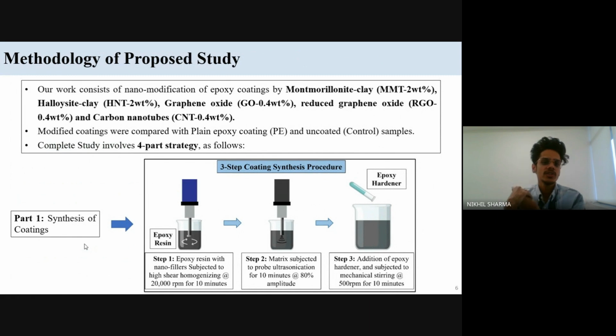In our proposed methodology, we nanomodified the epoxy coatings with 5 different fillers: montmorillonite and halloysite nanoclays at 2 weight percent, and the carbon allotropes at a low concentration of 0.4 weight percent. Montmorillonite and halloysite are used at 2 weight percent; graphene oxide, reduced graphene oxide, and carbon nanotubes at 0.4 weight percent. All modified epoxy coatings were compared with the plain epoxy coatings, the control samples, and coated samples.